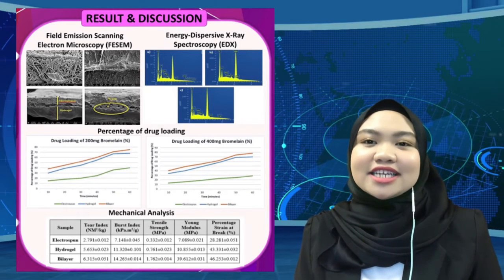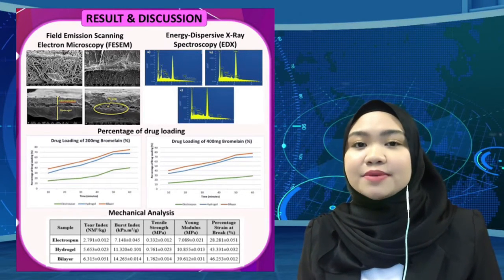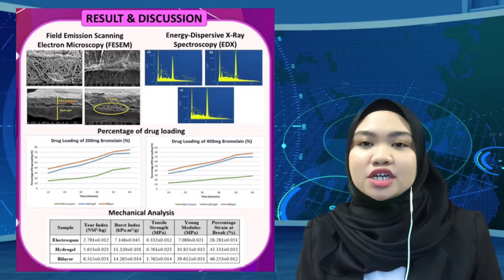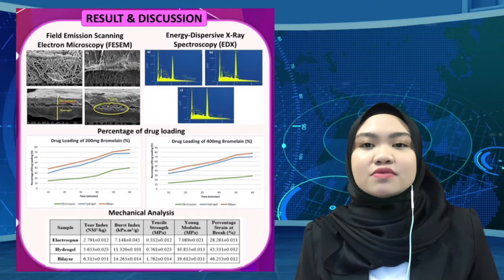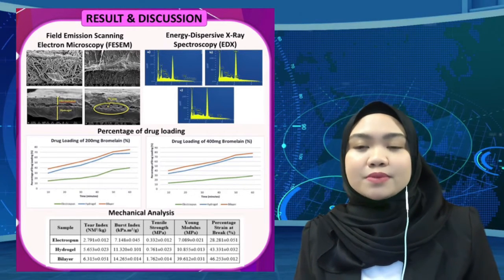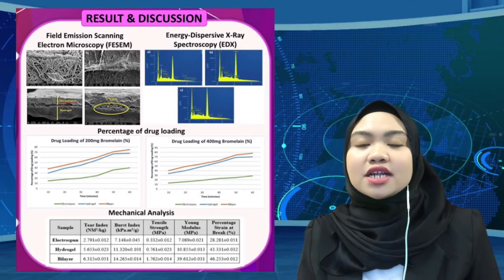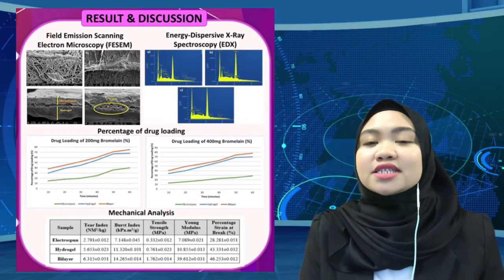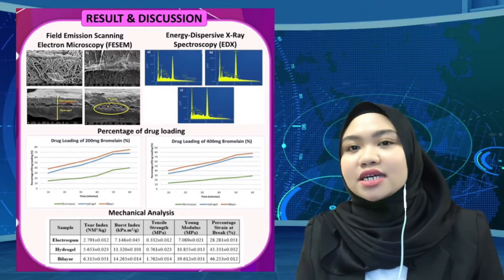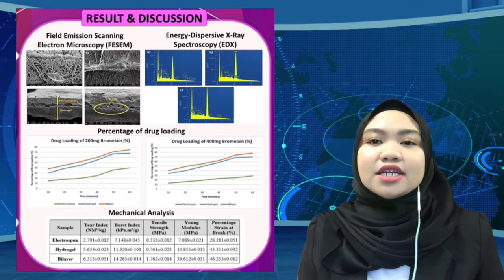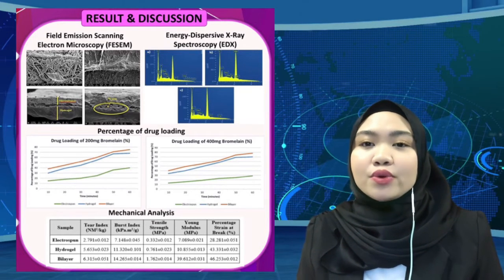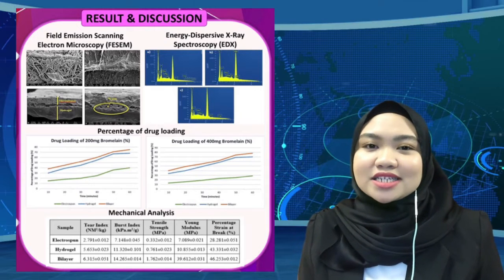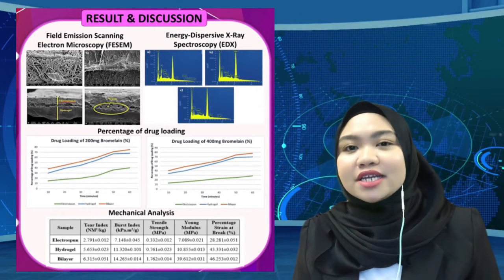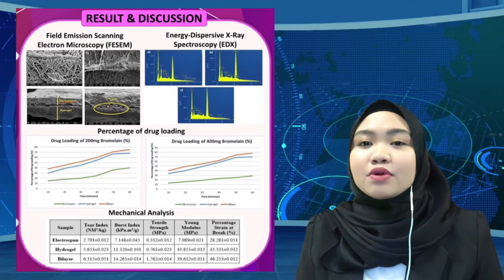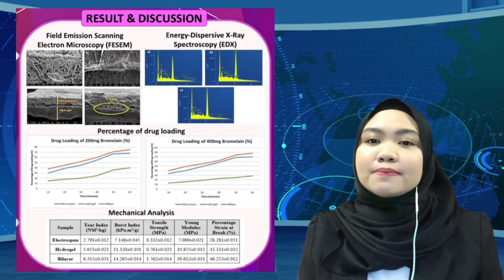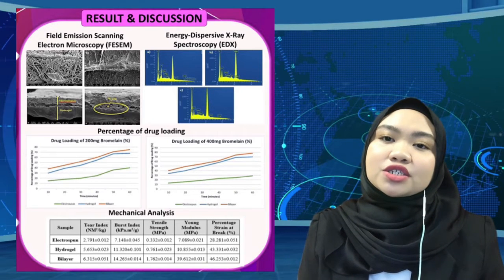As seen in the enlarged SEM image, the hydrogels exhibited homogeneous distribution and interconnected porous structure with no significant phase separation observed. The cross-section image of the bilayer composite, the combination of electrospun with hydrogel, shows a two-layer structure, in which the first layer is electrospun nanofiber and the second layer is a hydrogel. It can be seen that the hydrogel incorporates well with the nanofiber, with no gap between them. As a combination of electrospinning and hydrogel, the bilayer composite has a three-dimensional structure that provides a suitable microenvironment allowing cells to submerge and develop, as well as a three-dimensional structure for wound healing.